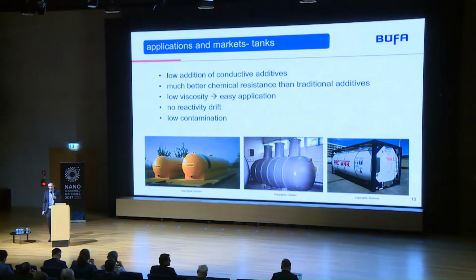And one big point for our customer in the production is, I call it low contamination, and that means if you use carbon black graphite, it's always black, and you have a lot of dust in your production site. And with these low amounts of Tuball, our customers like it, that they don't have to use this black powder, the normal one.